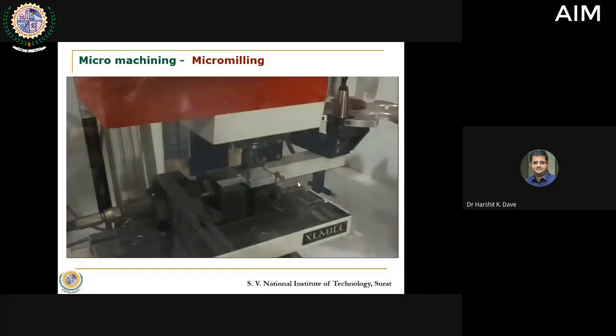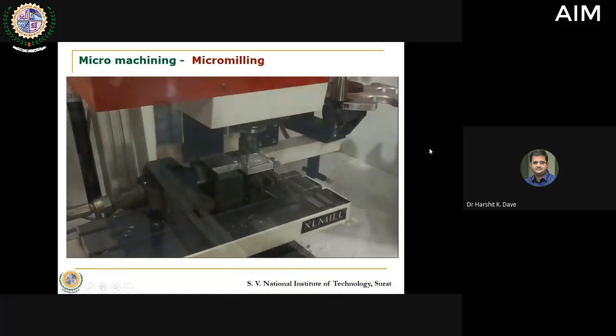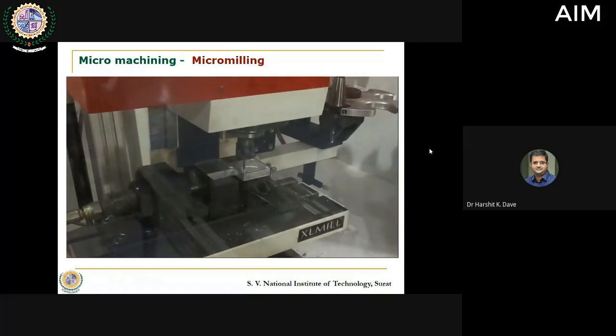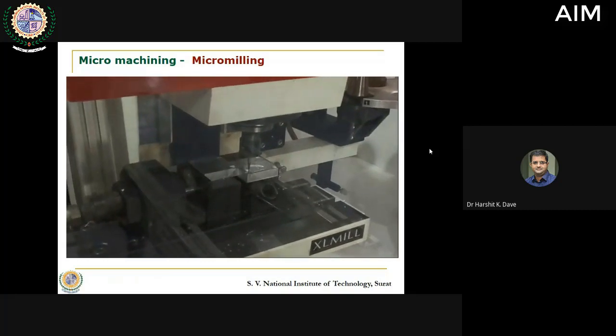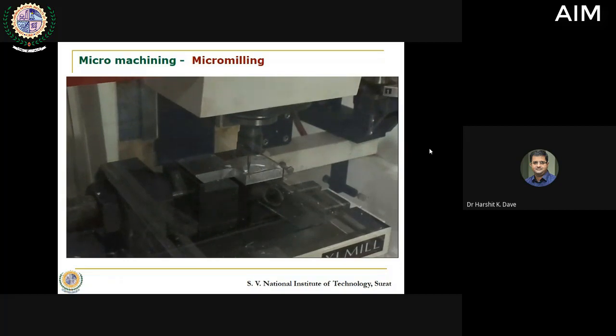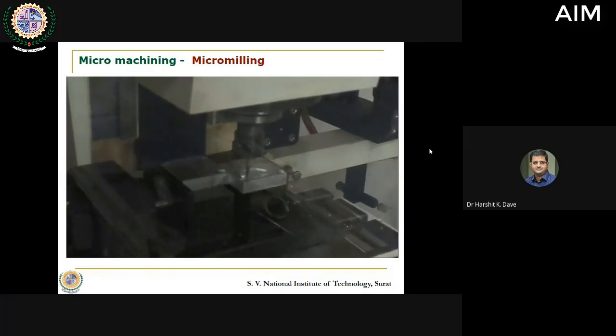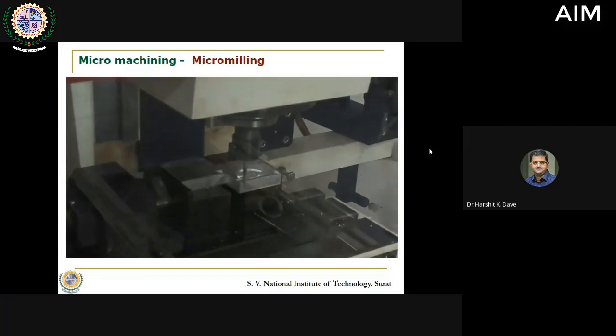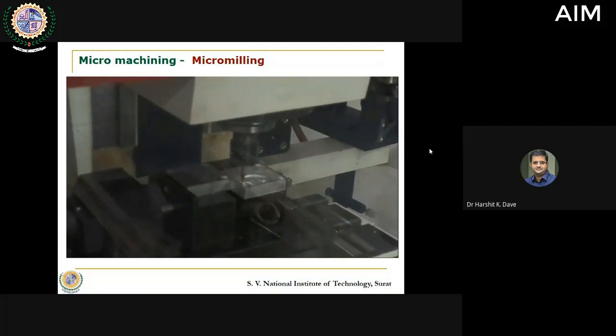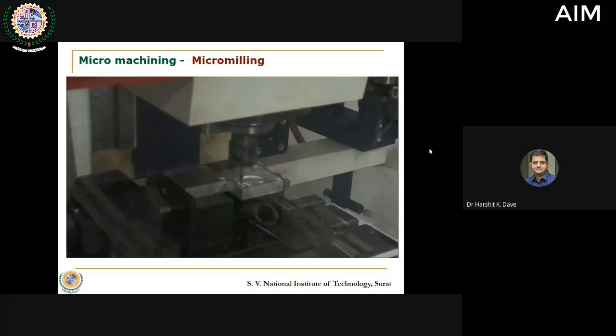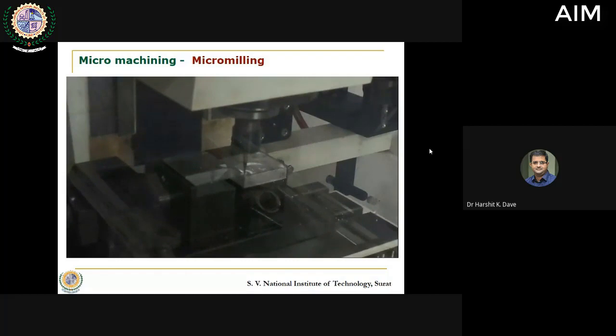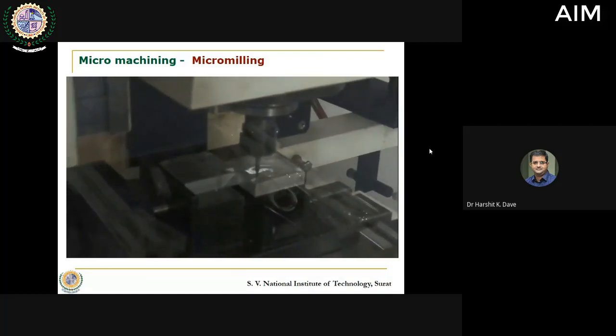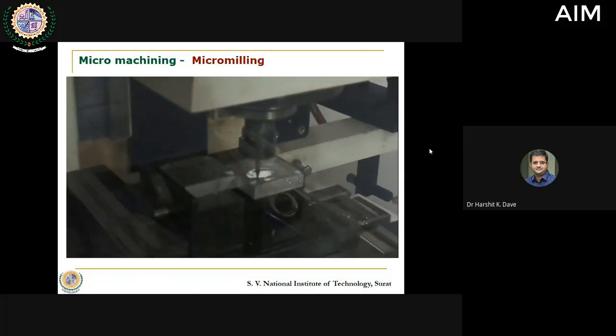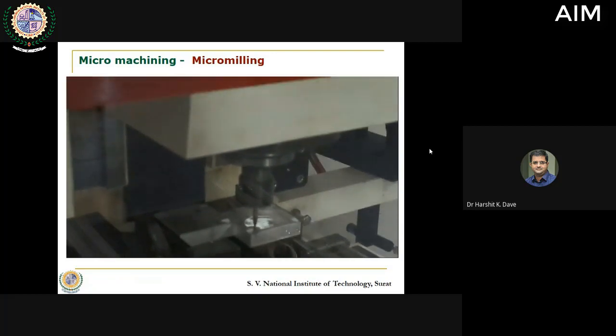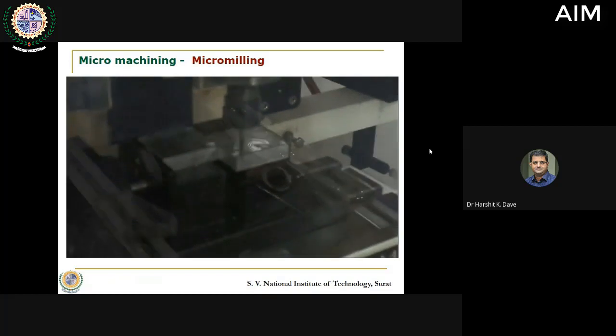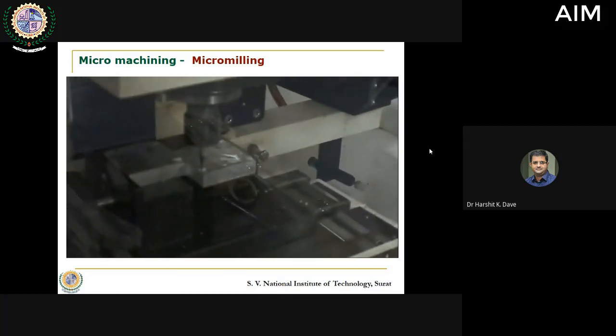You can see this activity being carried out. Here you can see that this is our XL mill, the MTAB CNC milling machine. Though the quality is poor because at that point of time we did not have proper equipment, even a mobile, to capture it, and there is a glass cover in between, because of which the recording is slightly poor. But you can observe that this step is being generated right now. The tool is passing over one of the sides, and then it moves along the other side. This is probably the edge of the first part. It is returning back, and one such entire layer is being removed. Now this is the second pass.